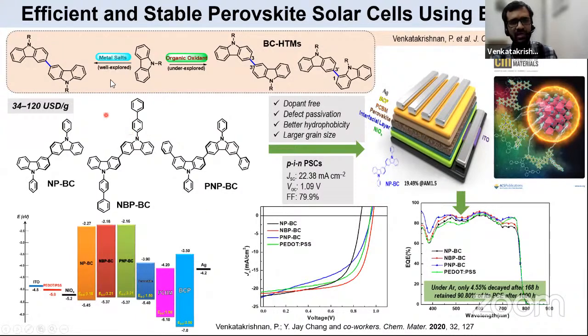And in our laboratories, we have recently demonstrated that synthesis of bicarbazoles is indeed possible, starting from simple carbazoles if you employ simple organic oxidants. By this way, you will be able to eliminate any metal contaminants, which are often reported to be contaminated with the hole transporting materials in the final step usually. Okay, so by replacing the metal contaminants by simple organic oxidants, you will be able to create bicarbazole hole transporting materials. So we looked in detail at these compounds. They have a twisted geometry because the ortho-hydrogen repulsion in the solid state would keep them slightly twisted, but not to the extent of the spiro-OMe-TAD that we talked about.